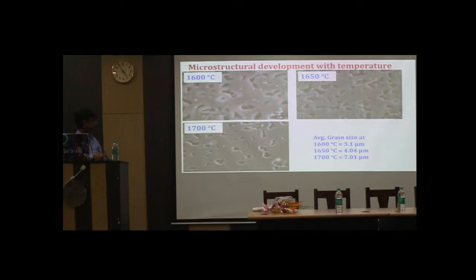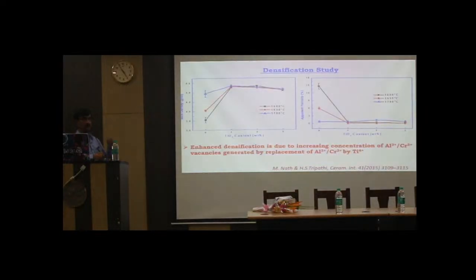I can skip some of the slides, but you see a lot of porosity is there, even at 1700 degrees, a lot of pores are there. So then to densify the material, we use titanium, 1, 2, 3% titanium. And you see, even with 1% titanium at 1600 degrees, the porosity level is just near 1%, or 0 to 1%. Even when we use only 1% titanium. And how this works: the titanium actually generates vacancies, either in the aluminum or chromium site, because of its higher valence, and that's why it favors the sintering.